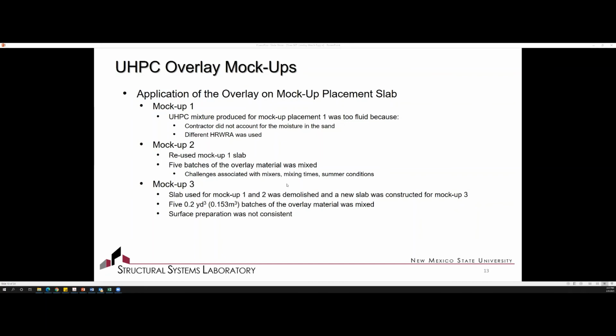Within this, we had 5 batches of the overlay material that was placed. Other challenges we were associated with were the mixers, mixing times, and getting the concrete down quickly. Summer conditions in New Mexico at the time were well above 100 degrees Fahrenheit, so we were definitely dealing with temperature conditions and making sure that the concrete was placed cool enough and so forth. So we addressed some of those issues, and then we ended up doing a third mock-up. This one had a slab that was first demolished, and we had a new slab constructed for mock-up 3.